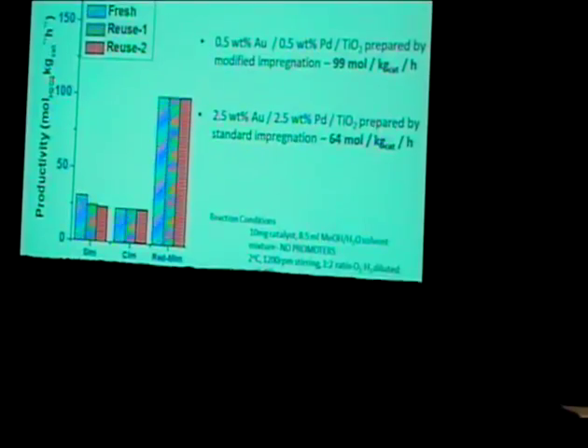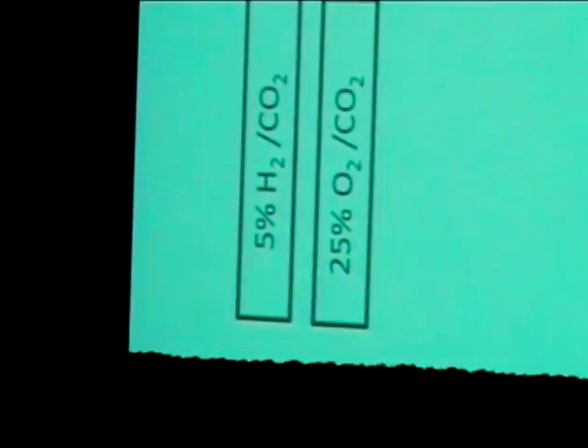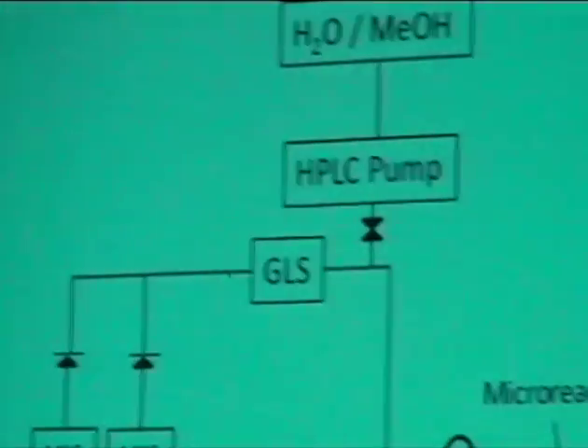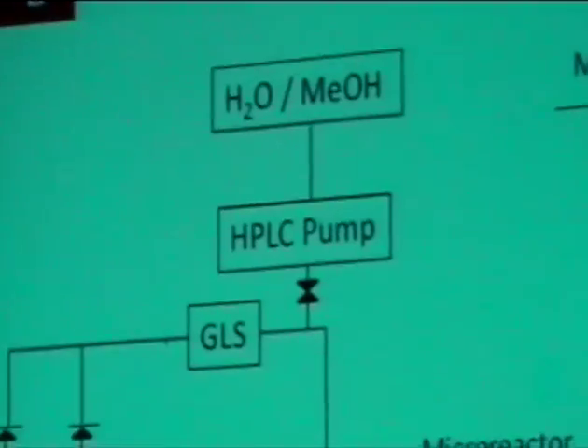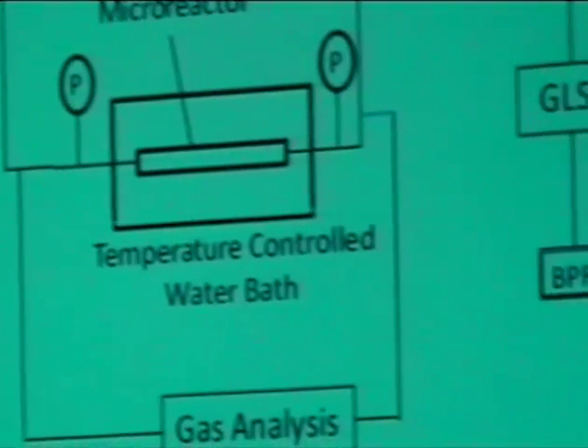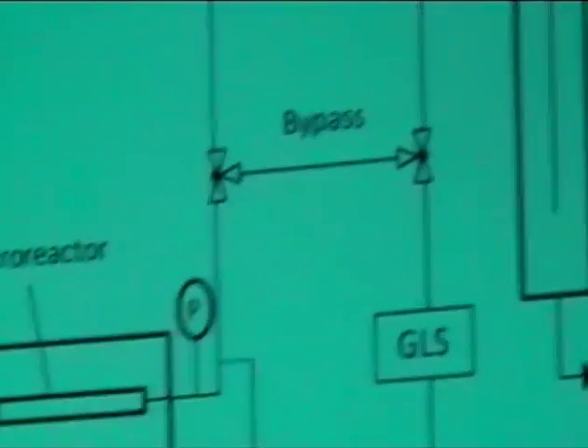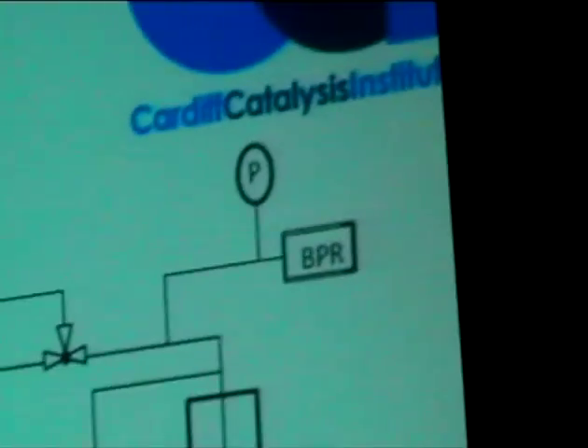To investigate the reaction conditions in a much more controlled manner, we've built a very small scale flow reactor to do the hydrogen peroxide synthesis in. So any reaction that can take away the yield by subsequent reactions, using a flow system should help to control, or at least understand this.